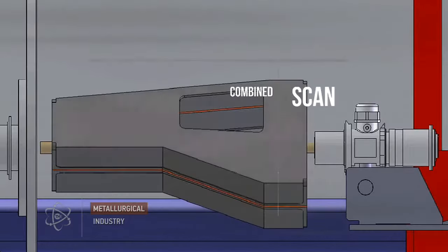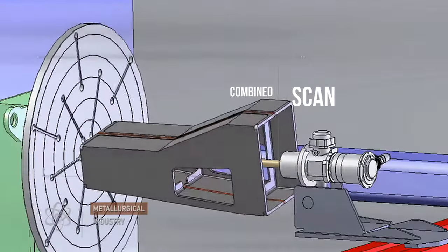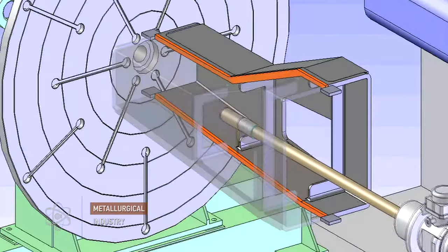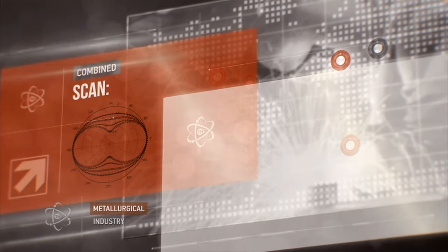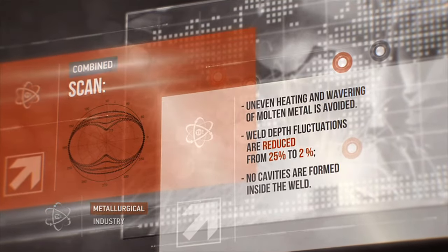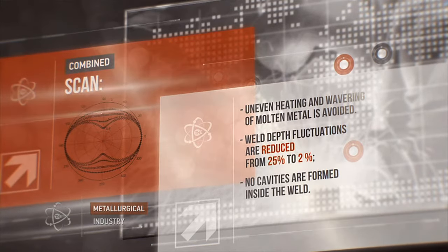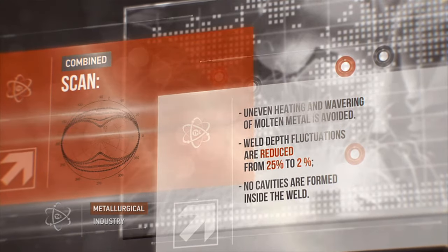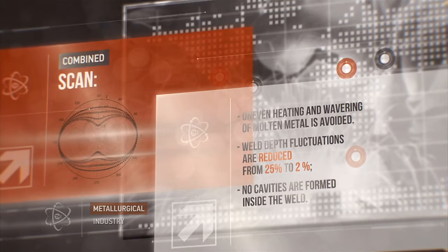The B.E.Paton Institute successfully applies combined electron beam scanning, wave, circular, etc. This helps to avoid uneven heating and ripple of molten metal. As a result, weld depth fluctuations are reduced from 25% to 2%, and welds have no cavities.